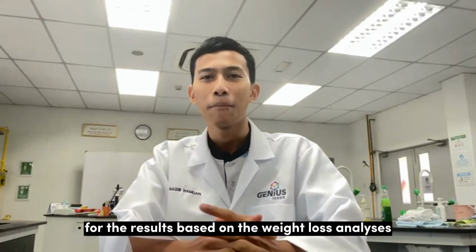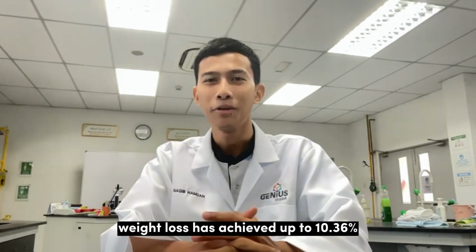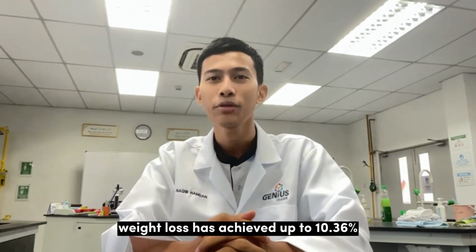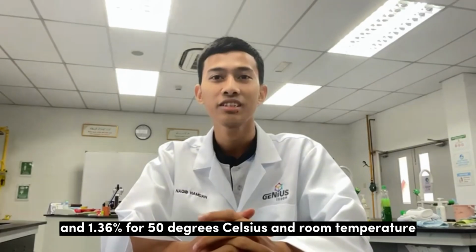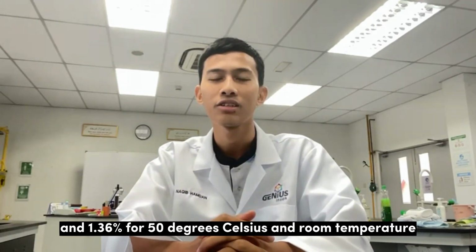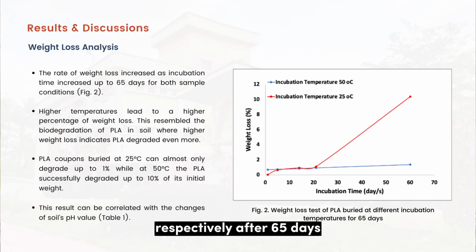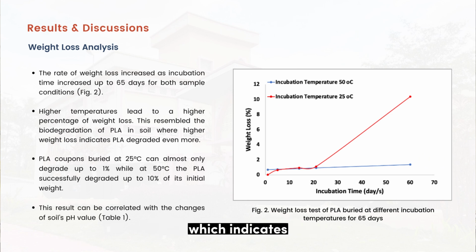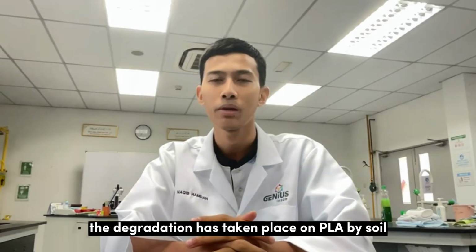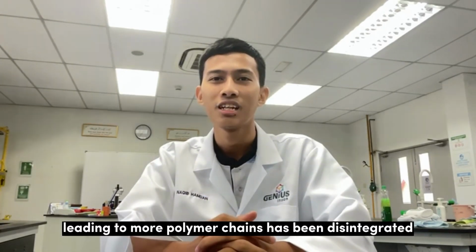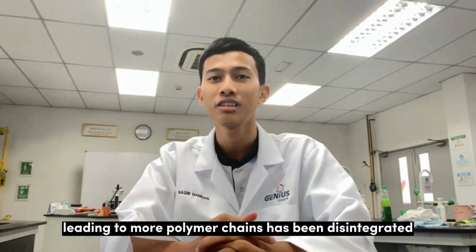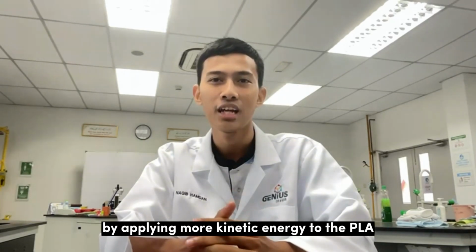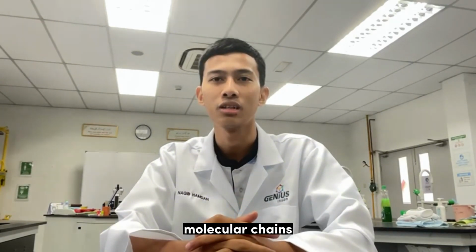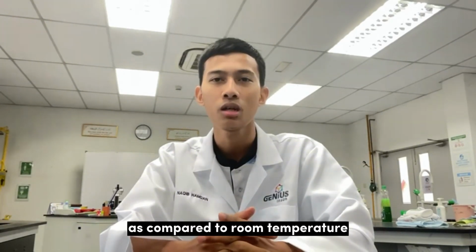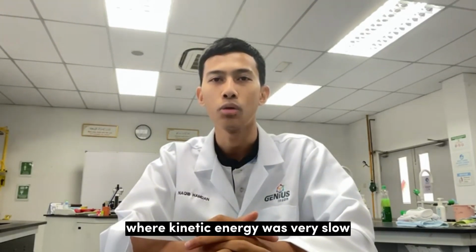For the results, based on the weight loss analysis, weight loss has achieved up to 10.36% and 1.36% for 50 degrees Celsius and room temperature, respectively, after 65 days, which indicates that degradation has taken place on PLA by soil. However, the higher temperature led to more polymer chains being disintegrated by applying more kinetic energy to the PLA molecular chains, as compared to room temperature, where kinetic energy was very slow.